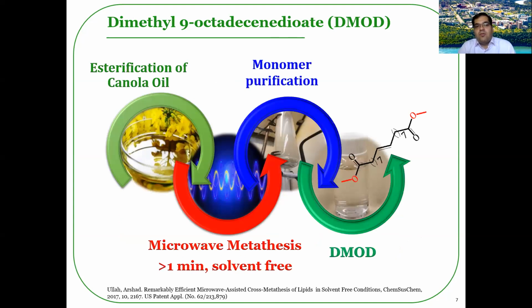For this purpose, canola oil was used to produce a bio-based chemical platform called dimethyl 9-octadecenedioate or DMOD through the esterification of canola oil as the first step for separating the free fatty acids from the glycerol. The free fatty acids were then converted to a mixture of different chemical platforms, including DMOD, through an efficient microwave metathesis reaction in less than 1 minute and in a solvent-free media. Then the DMOD was purified from the rest of the chemical platforms using column chromatography.